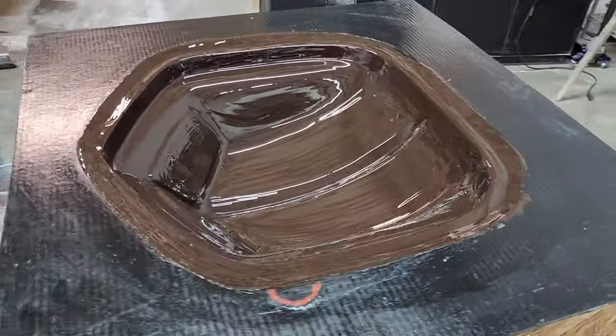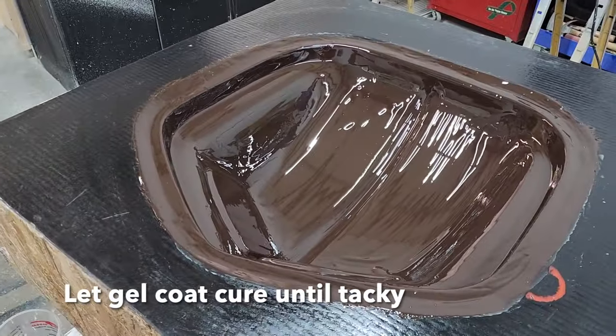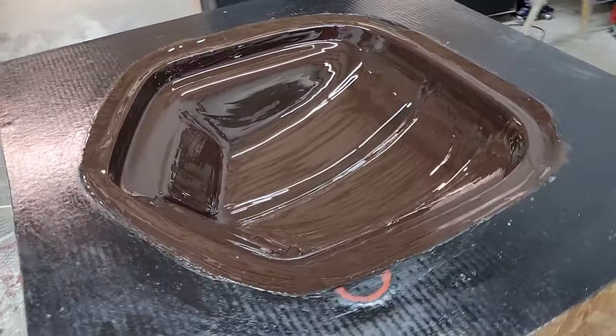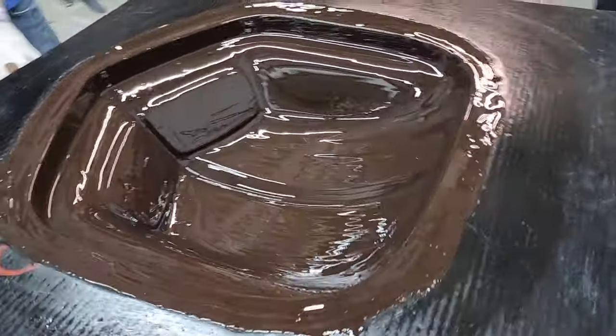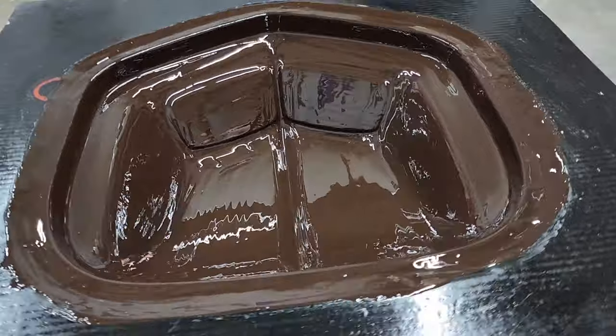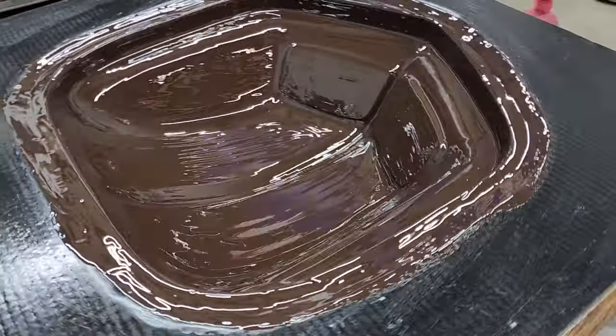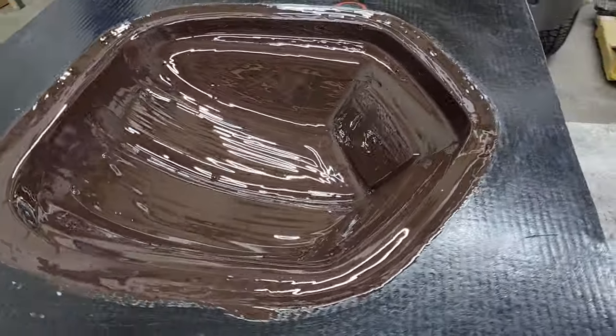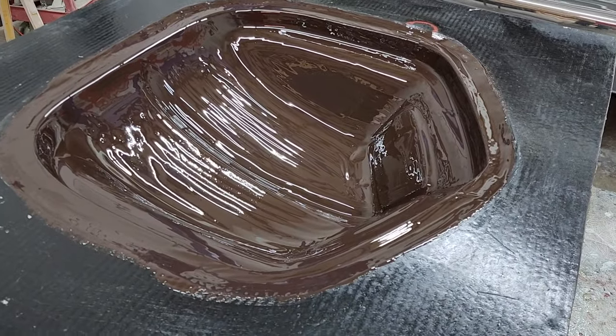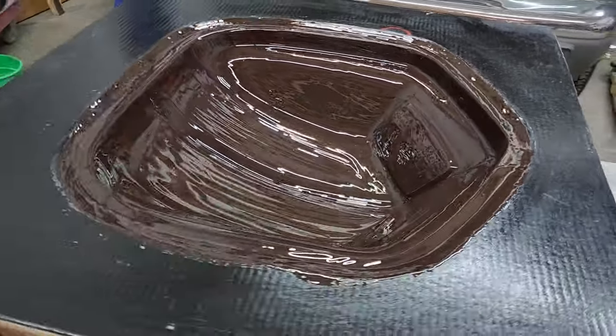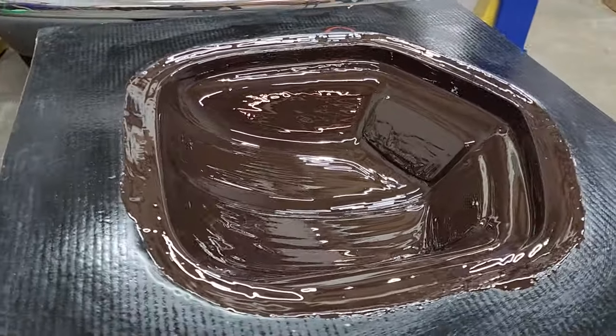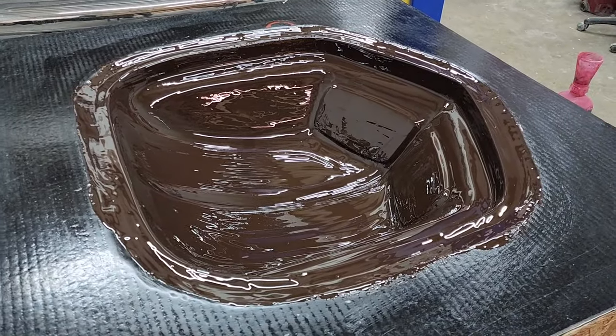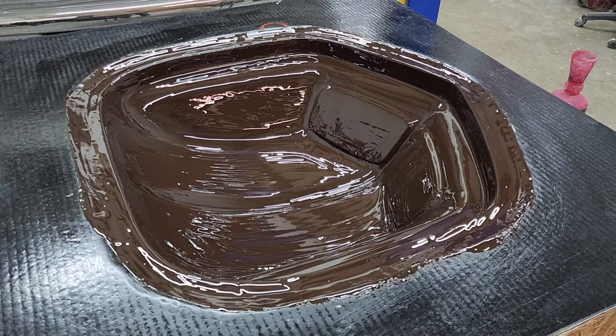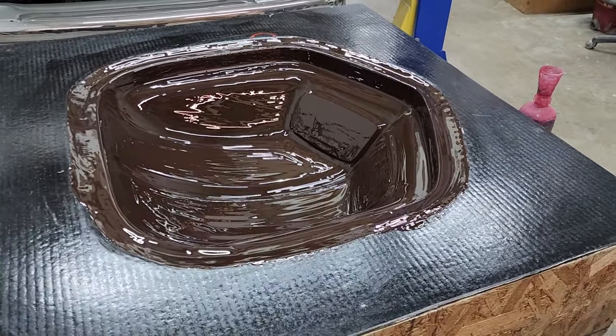Okay, so Brandon has finished laying it in. We just finished, so this is gonna take another minute or two for all the brush marks and stuff to settle out. But this is what you want, a nice consistent brushed pattern all the way around, no thick spots. The thick spots can cause you problems in the future. And what I mean by that is the gel coat can cure at different times. As I said, if it's thicker, it can cure faster. And you want it to be all the same thickness so that it cures at the same time.